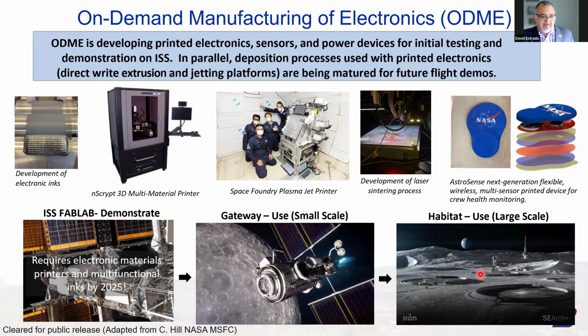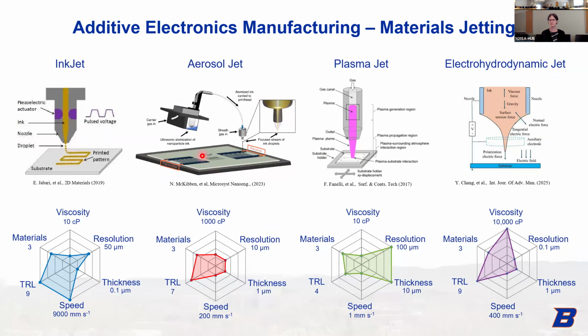So the need here really has been to evaluate different printers and develop new materials, right? So in terms of materials jetting platforms, we've worked with several different print modalities. Inkjet is by far one of the most technologically mature materials printers. It works on a drop on demand, where you basically apply an electrical pulse to a piezoelectric head. That pulse deforms the print head in a way that you can overcome the surface tension of the ink. The nanoparticle ink drops onto the substrate, and then translates to the substrate to print your device.